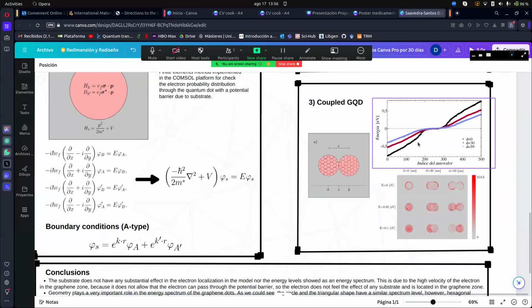Regarding the density of states, at 0 electron volts, the electron tends to localize at the edge of the quantum dots as expected. However, it is observed that at 0.05 electron volts, the probability density tends to spread between the two quantum dots, something that doesn't happen at 0.1 electron volts. From this point on, the probability density becomes concentrated in a single quantum dot, as we can see in the picture.